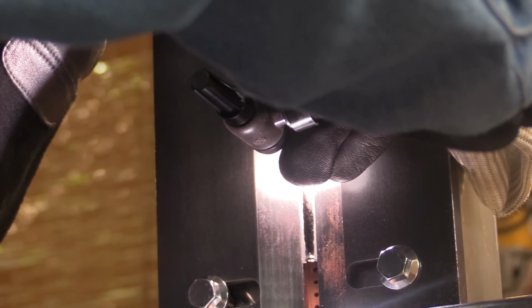Titanium filler rods get really sticky when they get hot, so you got to be really careful. You can't really scoot that filler rod into the puddle like you might on stainless steel. It really wants to grab like bubble gum onto the base metal, so you kind of got to aim to the hot part of the puddle.